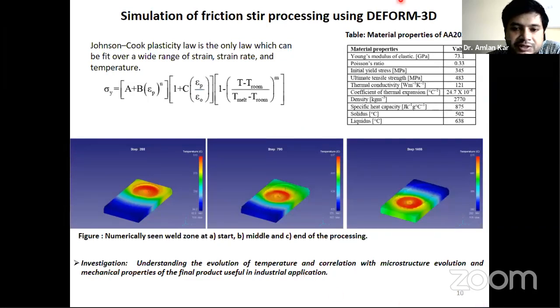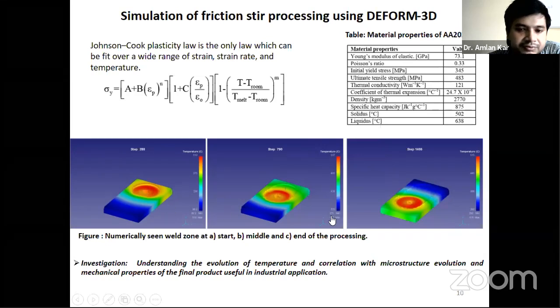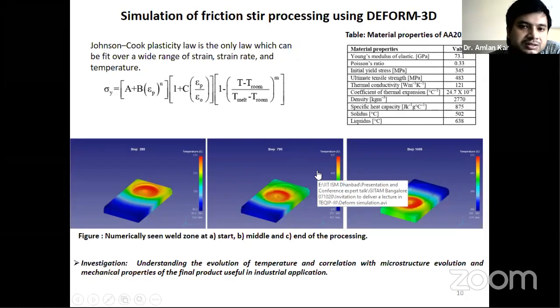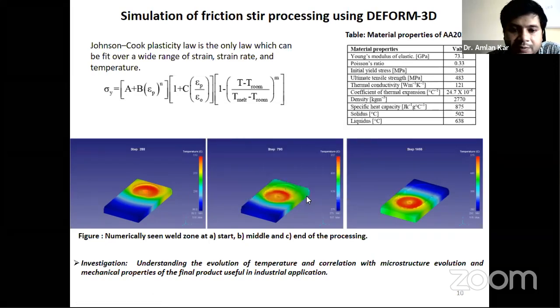While measuring the temperature, I was telling you that it could be low temperatures. But how are you sure this is a low temperature? For that, I have told you that the temperature below the shoulder is uniform. To understand the behavior further, we have also developed the friction stir process modeling using DEFORM 3D. You have seen this is only a processing model. I'm not saying that this fully justifies the model, but we can see whether the temperature below the shoulder is constant or not. So this is the primary work we have developed.